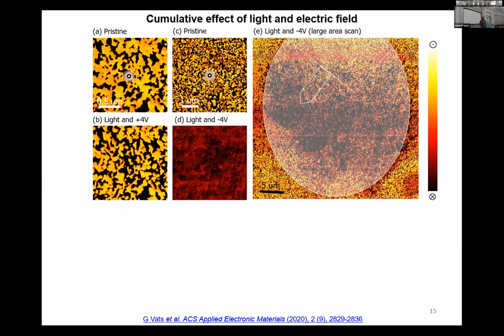So what is happening is, when I shine light, the conductivity of this particular area is tuned. It's enhanced by a few orders. And when I apply electric field at this particular point, it's spread over the whole area. And you see a large area switching, or I can say ultrafast movement of ferroelectric domains. And this is really interesting. This kind of thing was reported in the past, in the 80s and 90s on lithium niobate, but the required voltages and light intensity were too high. But here we are playing with very low voltages and a very low energy laser.